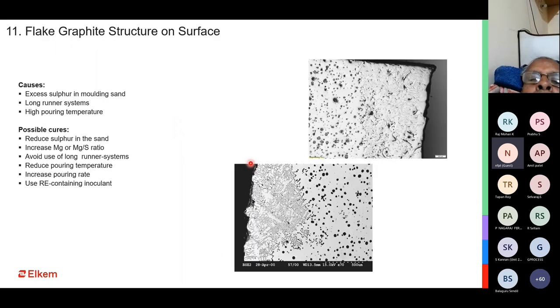Flake graphite structure on the casting surface, especially in ductile iron. We see a lot of ductile iron castings having graphite flakes on the surface, despite the inner part of the casting being very good in terms of nodularity. Why does it happen? It happens because of the interaction between the metal and the mold which has higher sulfur content in it. It can also happen when you have a much longer running system, because then a lot of sand sulfur comes into the system. It can happen when you have a higher pouring temperature.